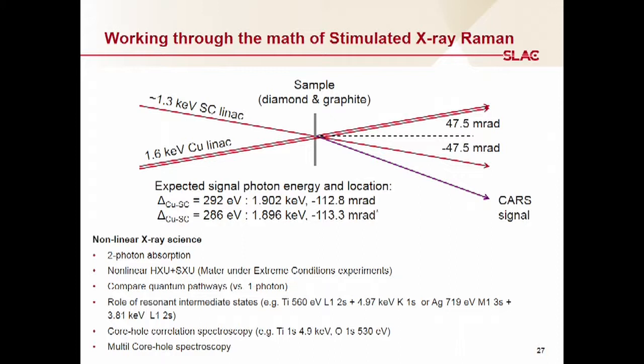As I said, you can think of two photons. You can think of some nonlinear MEC type experiments. You can think of multi core-hole spectroscopy. Thinking of, like, titanium has a K edge at 4.9 keV, oxygen has a K edge at 530 eV, and titanium also has an L edge at, I believe, 560 eV. So you can come in with those three photon energies and make different core holes, and probe how the electrons interact with each other. These are things that I want you to think about when you're designing experiments. This has never been done, and the field's pretty wide open.